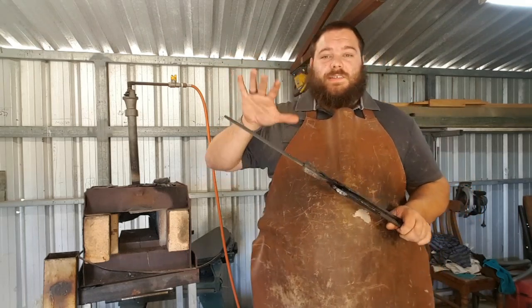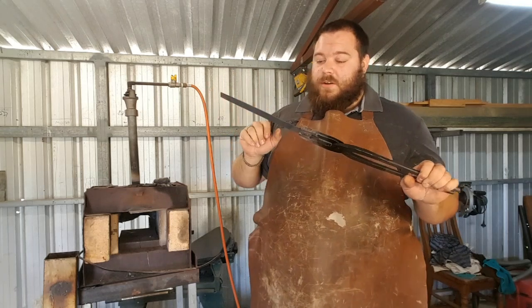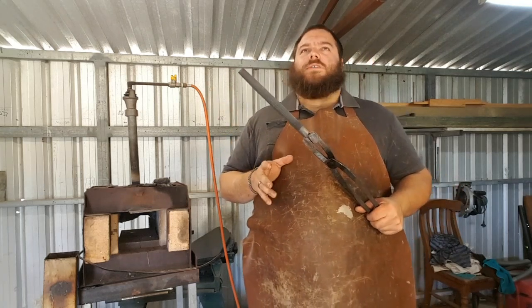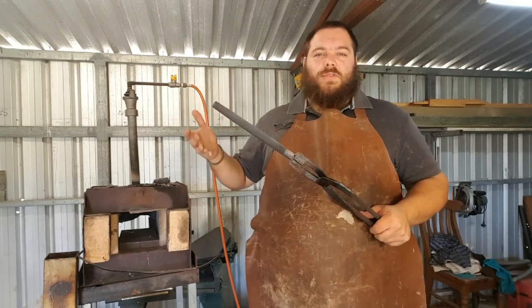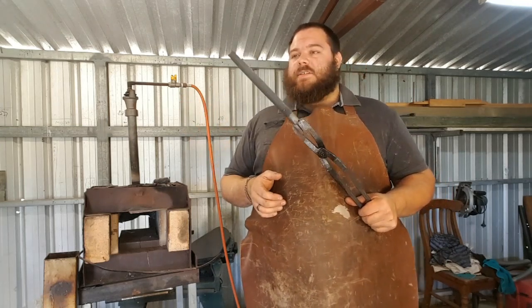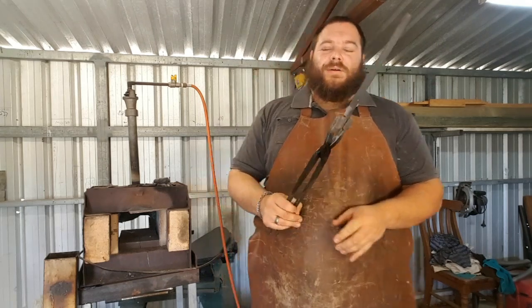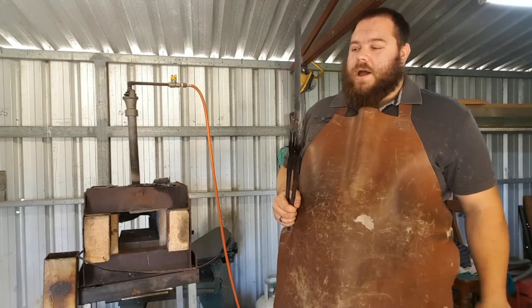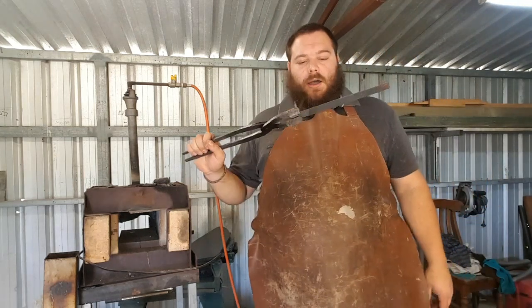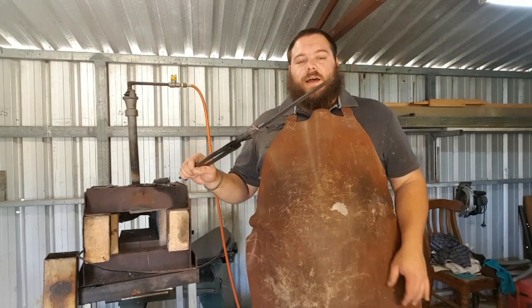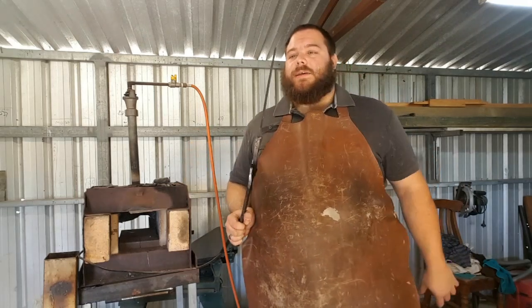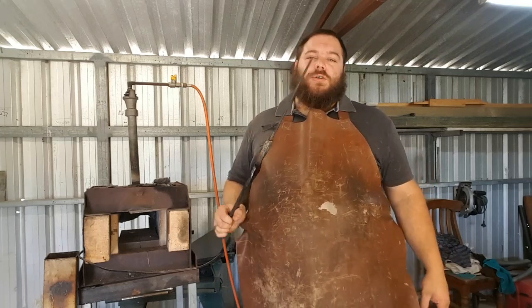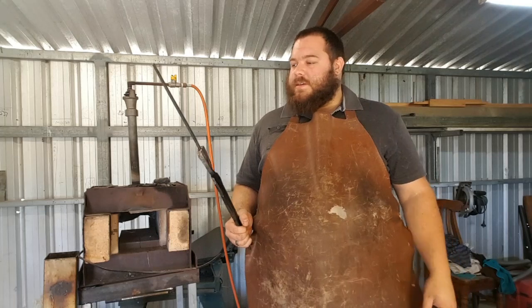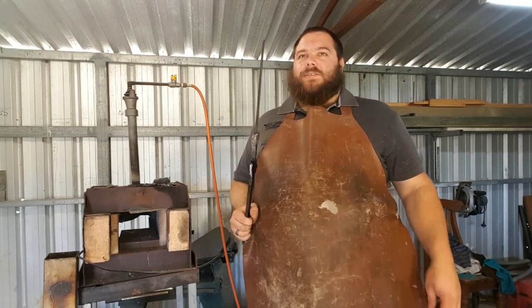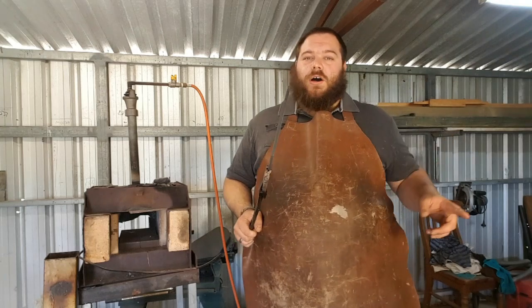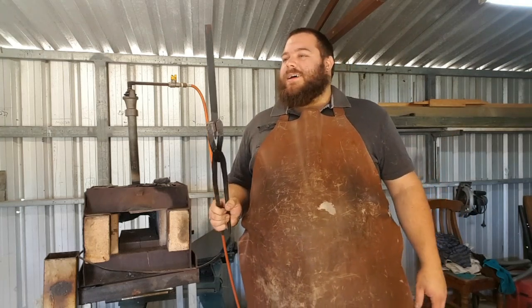I still wouldn't want to touch it because it's still sitting at around 600 degrees, maybe 500 degrees Celsius. Sorry, not Celsius, Fahrenheit. About 230, 240 degrees Celsius. I'm going to keep trying to do that, but if I get it wrong, I apologize. So it's still quite hot, but this is now normalized, so it should be nice and soft. And the best way to test that would be to bend it. I'm not going to do that because I know it's soft, but if you wanted to test your normalization skills, bend it. If it snaps, then you've either not normalized it enough or heated it way too hot and then waved it around and tried to cool it.